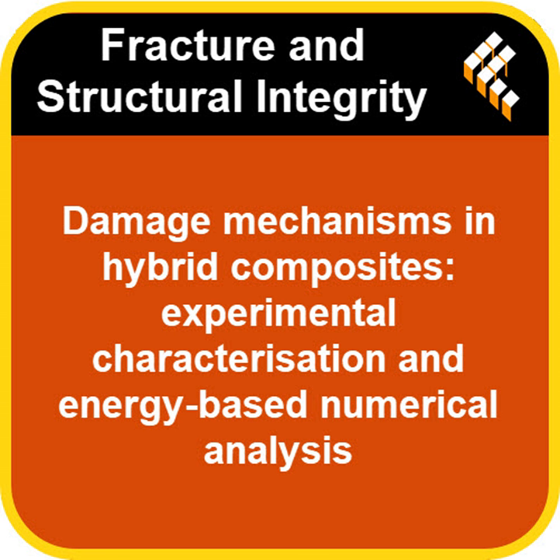Yeah, let's summarize. They really emphasized the big differences in bending strength and displacement between pure carbon and pure glass materials, with the hybrid mixes falling somewhere in between, as expected. Okay, baseline established. But the crucial point they kept coming back to was how important it is where you put the glass fiber layers. It's not just how much glass, but where it is. Location, location, location. Exactly. Putting glass on the side being compressed, the compression side, led to higher strength and less bending before failure. Putting glass on the side being stretched, the tension side, resulted in lower strength, but more flexibility, more displacement before it broke. Got it. Key design choice right there.